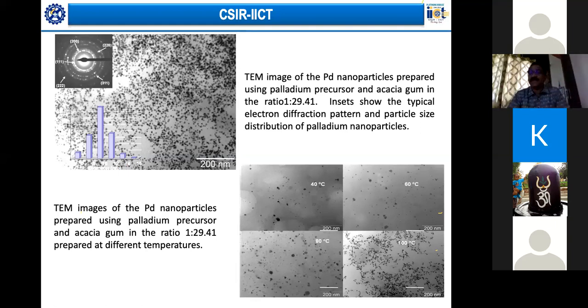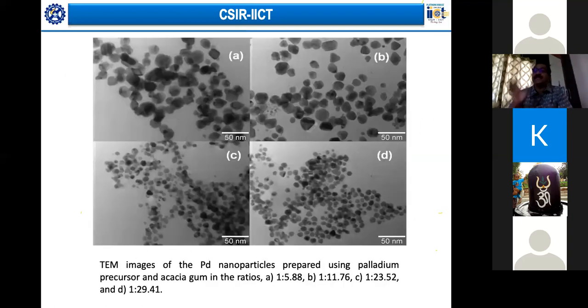Here again, we can play with the concentration of gum, and that results in a different particle size. So that's what we did here. As this is at the lower concentration, as we increase the concentration of the gum, you see that the particle size is less compared to the initial one. When the concentration is less, the steric hindrance on the growth of these nanoparticles is also less. That is the reason they grow into bigger particles. But as the concentration of the gum is increased, the hindrance is also increased, and that limits these particles to lower size. That is why at higher concentration, we could have these particles of 8 to 10 nanometers in size, uniform in size.